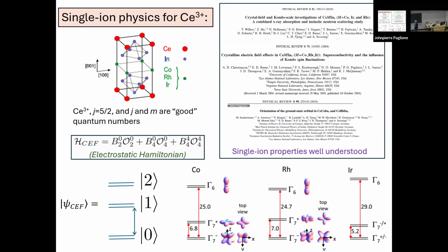We then put that in the crystal electric field, and a cute way of writing that, you could go off and do the Coulomb business, but this will get you there too. This is just equivalent operators called Stevens operators. It doesn't matter. You get the same answer either way. But what you find is that if you put this in the electrostatic field, you end up with 3 doublets here. So you see there's 6. It's always good to count and make sure you haven't lost anybody.